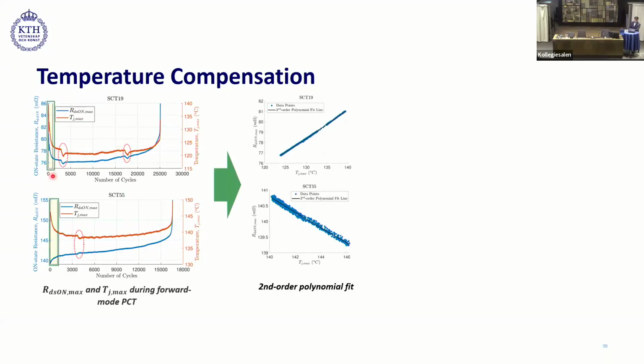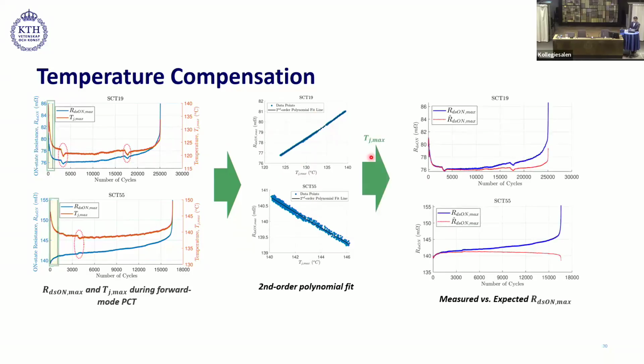If we focus in this highlighted region, so we use the TJ max and RDS on max data from this highlighted region, and then we plotted RDS on max with respect to TJ max. One important thing to note here is that RDS on max in SCT19 exhibited positive temperature coefficient, while that in SCT55 exhibited negative temperature coefficient. So using these samples, we derived the second order polynomial fit function. And then by feeding the maximum junction temperature, TJ max, in this second order polynomial fit function, we calculate the expected value of RDS on max, which is represented by red curve here.